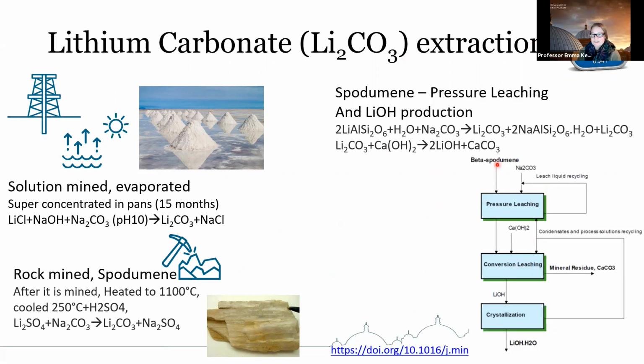Now, what I've done here is put in a lithium hydroxide production route. And this is because lithium hydroxide is quite often used as a primary source for manufacturing of materials in the lithium-ion battery space. And again, interestingly, sodium carbonate is used in the production of lithium hydroxide. In this particular route, lithium is leached again from beta spodumene, but under a hydrothermal process. It's then reacted with calcium hydroxide or lime to produce the lithium hydroxide, which is what we use for manufacturing of materials for lithium-ion cathodes in particular.